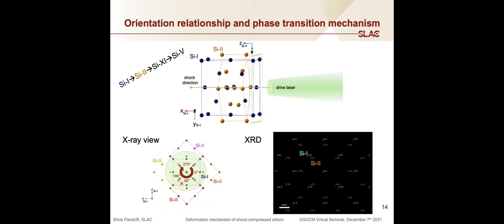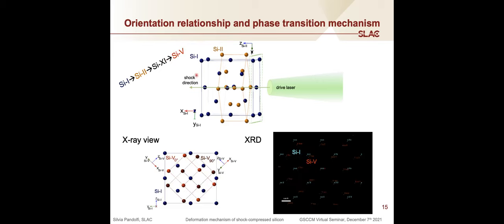However, this equivalence of the different orientations is lost as we keep progressing through the sequence of high pressure phase transitions, because when we go from the silicon two to the silicon XI, we have a deformation from the tetragonal to an orthorhombic structure. So this A equal B symmetry is lost. And ultimately, when we get to the silicon V phase, which is the one that we have observed and we're interested in, this phase transformation sequence would result in two non-equivalent crystalline domains rotated by 90 degrees with respect to each other that would give this X-ray diffraction pattern for single crystals compressed in our experimental geometry.